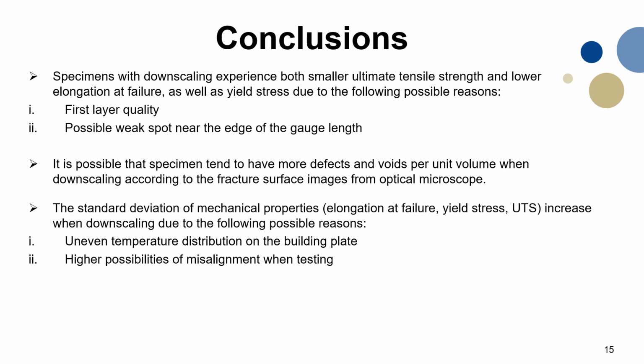And next, there's a higher possibility of misalignment when testing. Especially for the scale of 30%, the specimen gets really small for testing, and there's a very high possibility of misalignment, where you're not putting the specimen vertically on the testing machine.